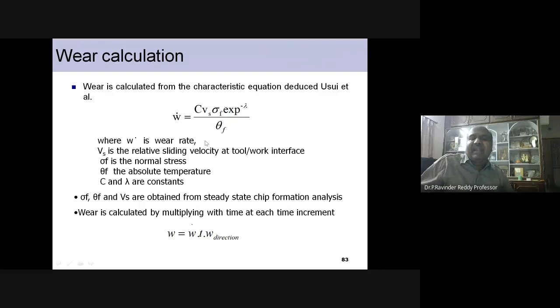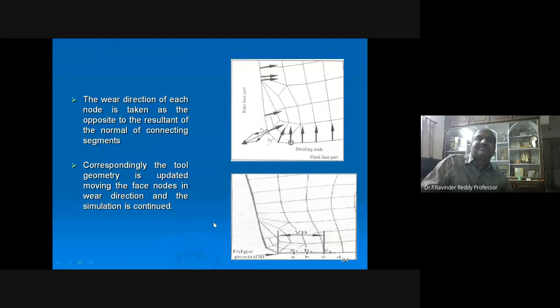And this is a wear rate which we can calculate, with C and lambda as constants, and W dot is wear rate, Vs is the relative sliding velocity of the tool, sigma F is the normal stress, theta F is absolute temperature. The sigma F, theta F, and Vs are obtained from the steady state chip formation analysis. Wear is calculated by multiplying with the time at each time increment. Then you can calculate those.